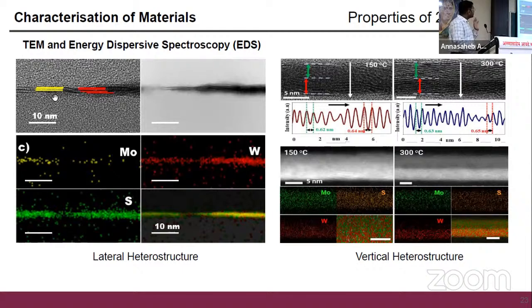This is the image of in-plane heterostructure formation, or lateral hetero junction formation, which was prepared by me. Here you can see two different regions for Mo and W and the sulfurization region, and also the layered formation.